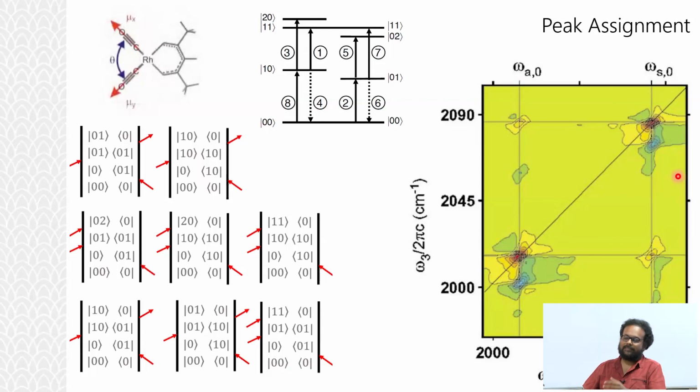And if you look at the imaginary part, which I'm not going to show you here, it's going to look dispersive. There is a very specific phase which is imposed on the optical response because of the system, and it's normal to find this exact phase shift. It so happens, this absorptive-dispersive behavior: the real is always absorptive, the imaginary is always dispersive. However, of course, when you're trying to do research, you will find things, and we found in one scenario exactly the opposite. There was a phase scrambling, and that's because of many-body interactions. Many-body interactions can scramble phase, which adds additional phase basically. We'll not talk about it, just keep in mind.